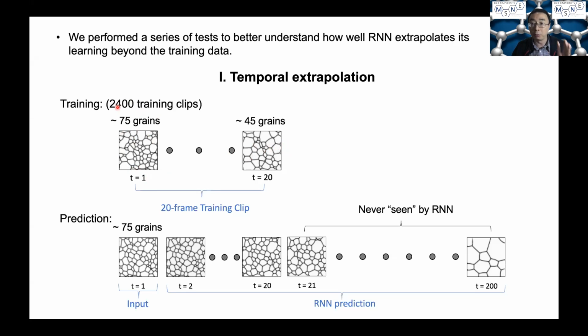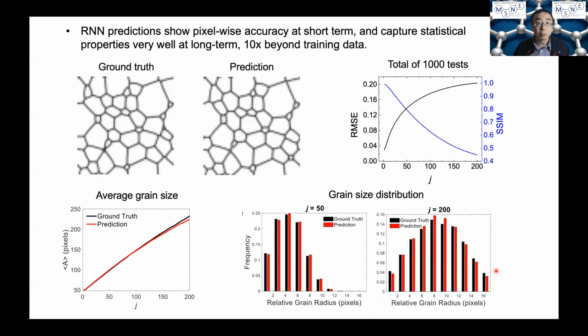After the model is sufficiently trained and converges, we let the trained model make a prediction based only on one input frame, which serves as the initial polycrystal structure configuration. Then the model needs to predict the next 200 frames of how the polycrystal evolves over time. Here I want to point out that 90% of the predicted frames, from frame 21 to 200, actually fall outside the time span of the training data, which only covers the first 20 frames. So the configurations in these 90% of frames have never been seen by the RNN model. This serves as a test of the temporal extrapolation capability, up to 10 times that of the training data. And the result is actually quite satisfactory.